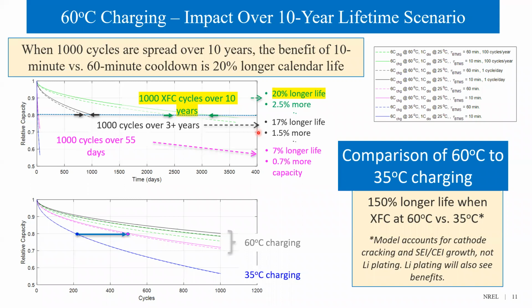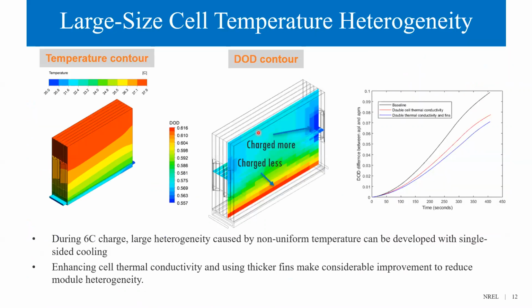The model estimated 150% longer cycle life when 6C charging at 60 degrees Celsius compared to fast charging at 35 degrees Celsius. It's worth mentioning the model accounts for cathode cracking and SEI growth, not lithium plating. Lithium plating will also see benefits.